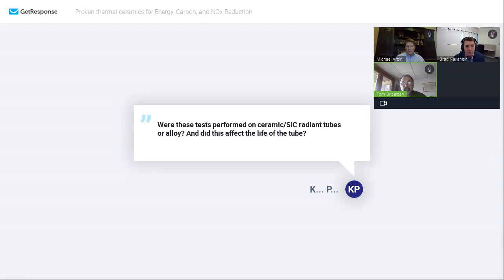So Tom, maybe you can expand a little bit, because this question comes up a lot about temperature capability of our products versus alloys. So the working temperature of the material is 1350 degrees Celsius. Most alloy radiant tubes that I know of operate in the temperature range of 1000 C, maybe as high as 1150 C. So the silicon carbide material is actually perfectly matched for this application.